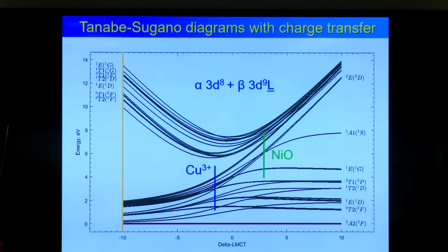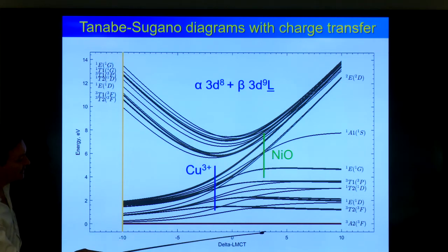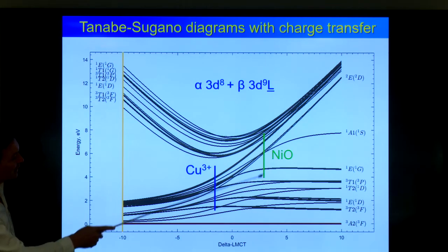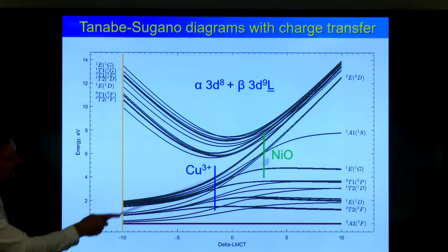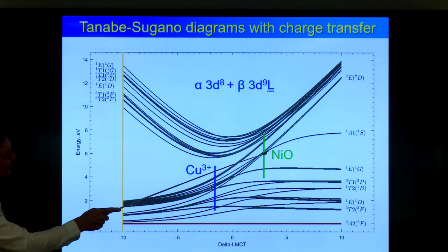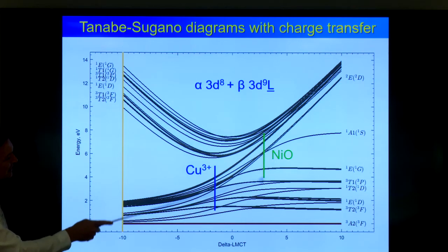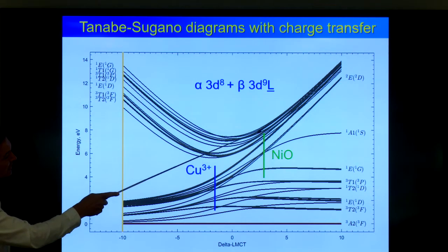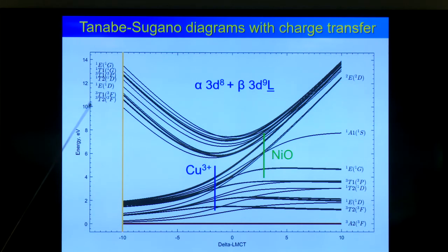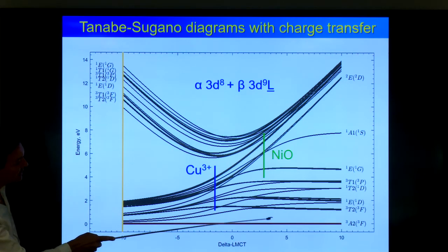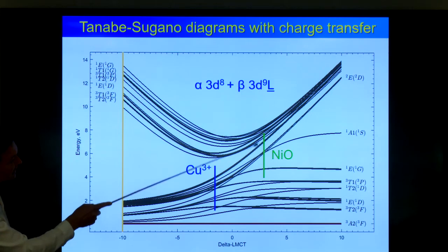Nickel oxide is actually here, at delta is 3. So then you see that your multiplets are already a little bit compressed. These are the multiplets we see in RIXS later. These are the optical excitations. And you see your charge transfer states relatively close in energy. So an optical spectrum will show the excitations of the ground state to all these excitations, and then the charge transfer.